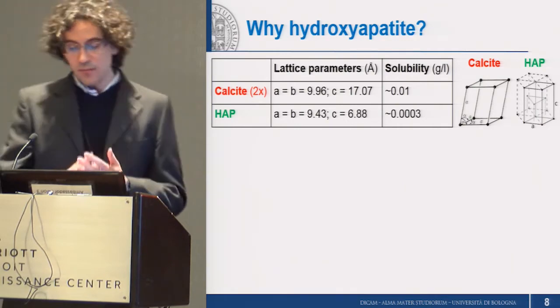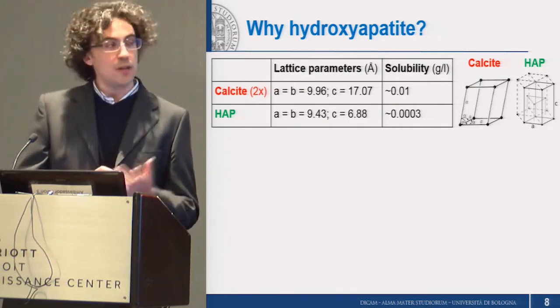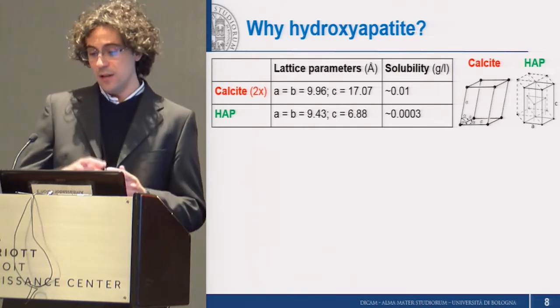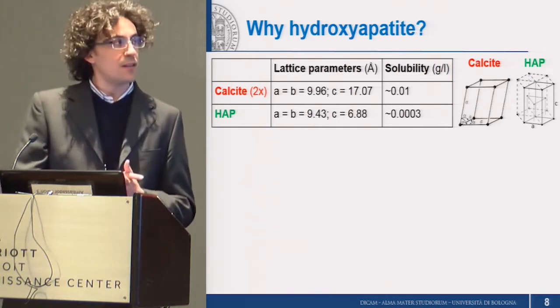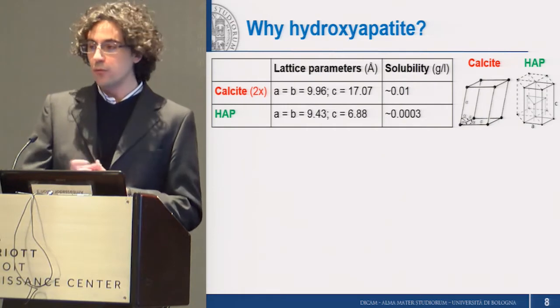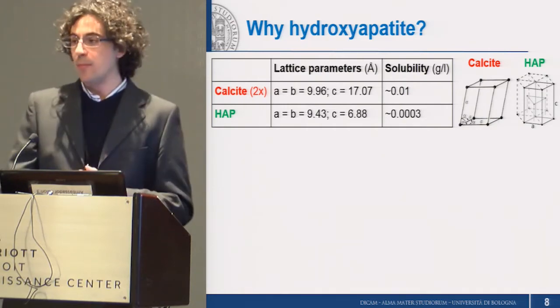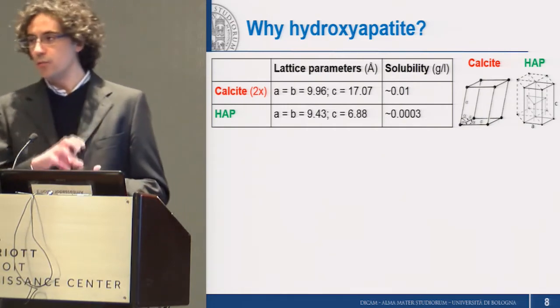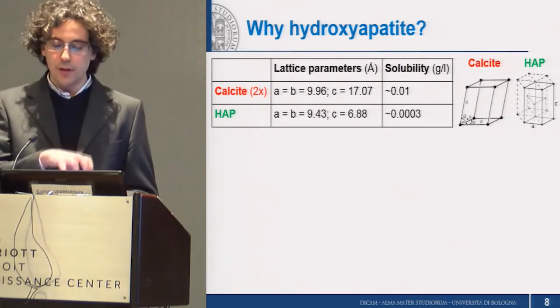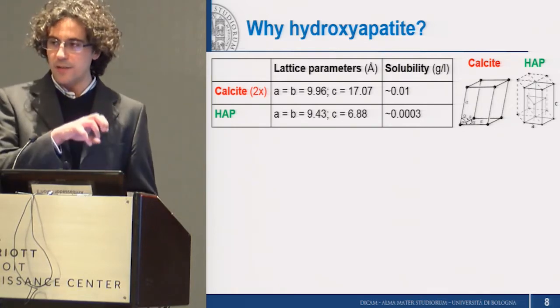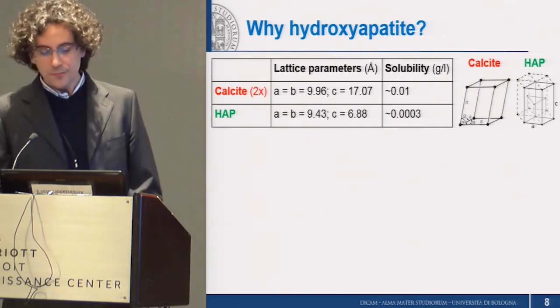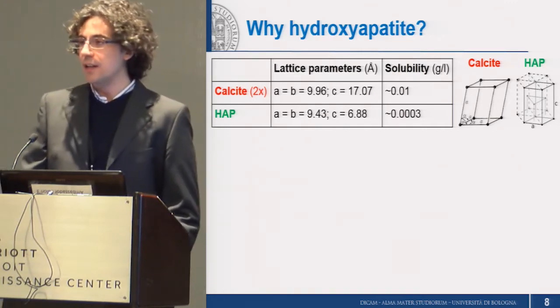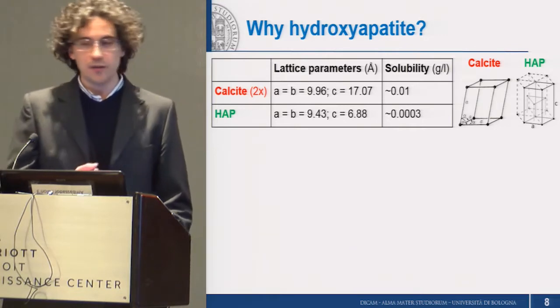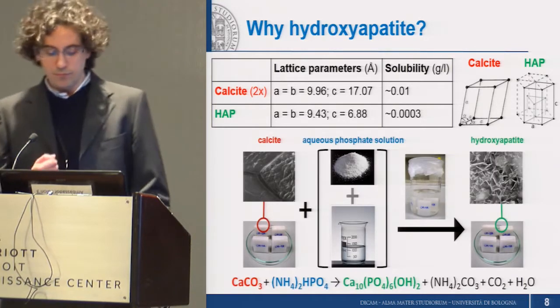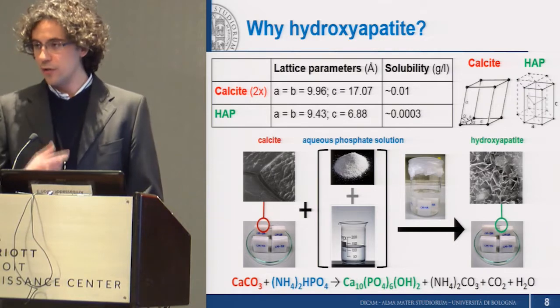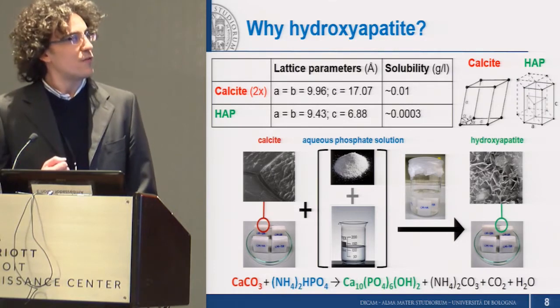And at the same time, it has a quite good match in terms of crystal structure, being rhombohedral for calcite and hexagonal for HAP, and a quite good match in terms of lattice parameters, so that at the beginning we hoped that epitaxial growth of HAP crystals could take place over calcite. Based on biomedical literature, because as I mentioned, hydroxyapatite is widely studied for bone regeneration and tooth preservation, let's say.